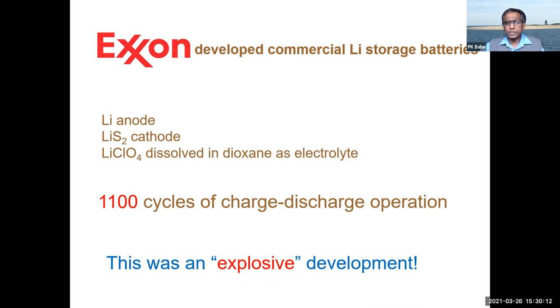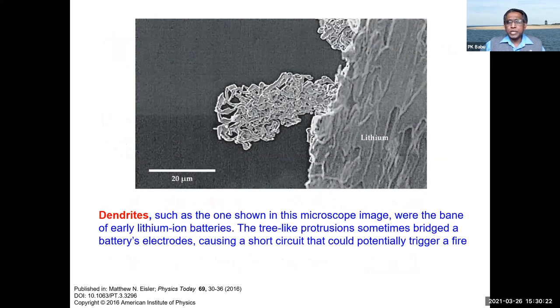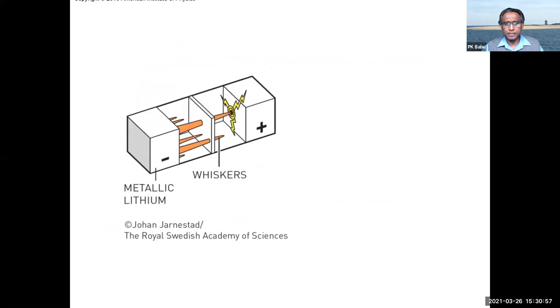And this was an explosive development in the field of battery, literally an explosive development, because during the charging of such a battery, when lithium ions are coming back to the anode to get deposited as lithium, scientists observed that, like the stalactites growth that you have seen in certain caves, the lithium atoms which are coming back to the anode started growing with tree-like protrusions known as dendrites. And sometimes they could bridge the battery electrodes, as shown in this particular cartoon.